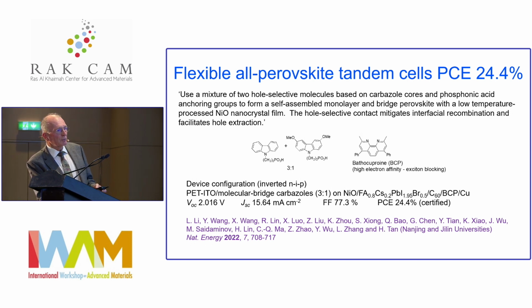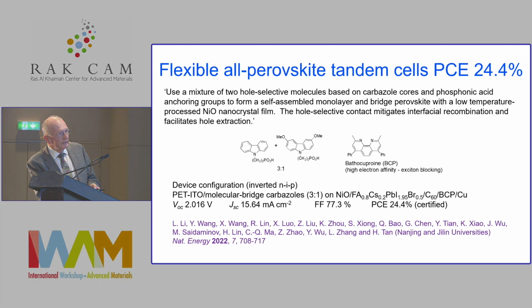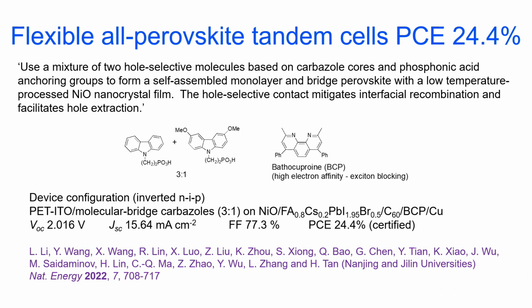And so it's quite a complex structure again, but here we see it. Basically, the active layer is a combination of the formamidinium and the cesium perovskites, but they use C60 and bathocuproine to deal with the charge extraction. So that's an impressive result, 24.4%.